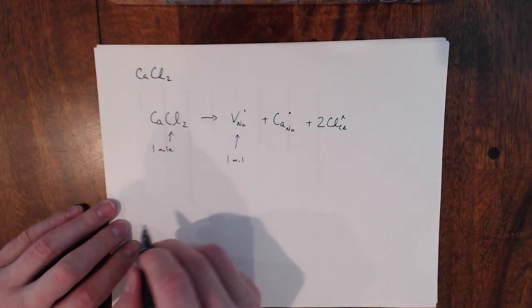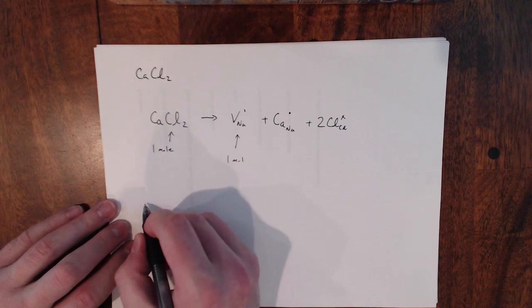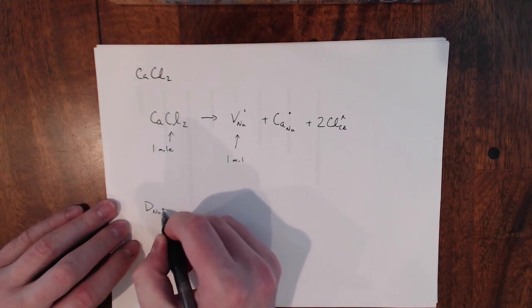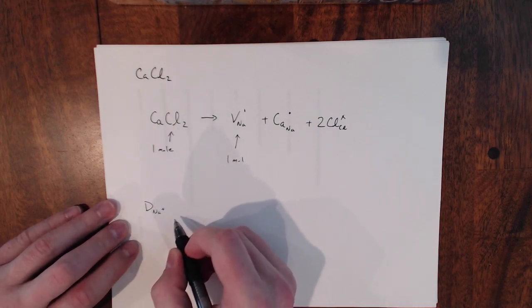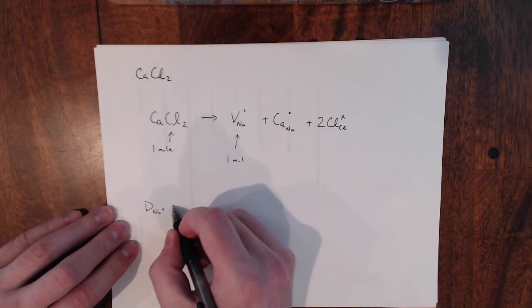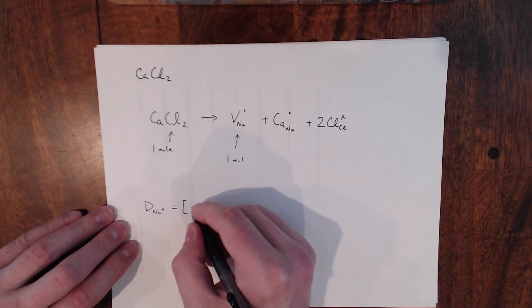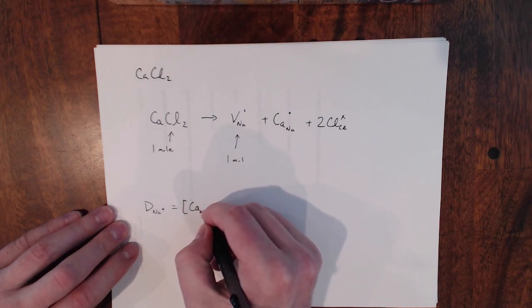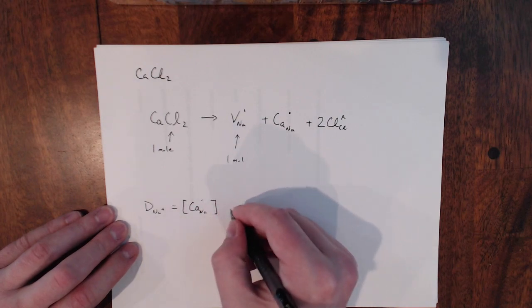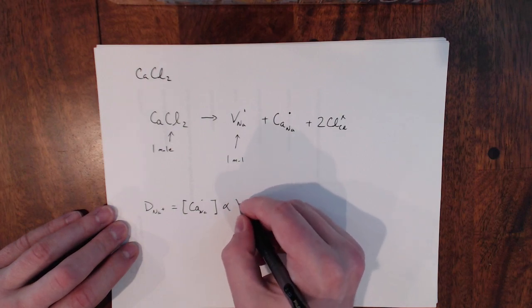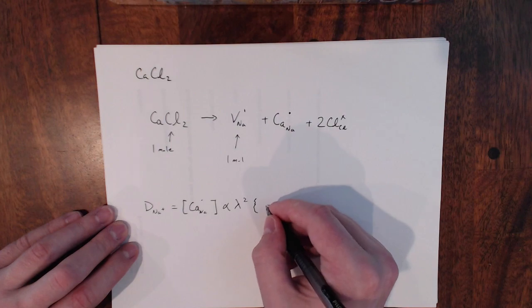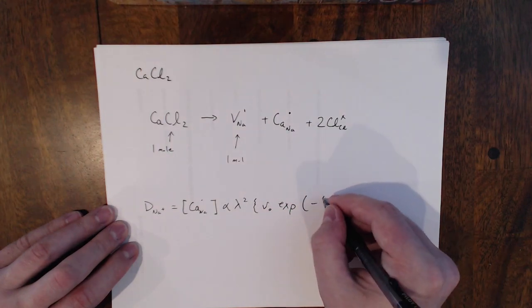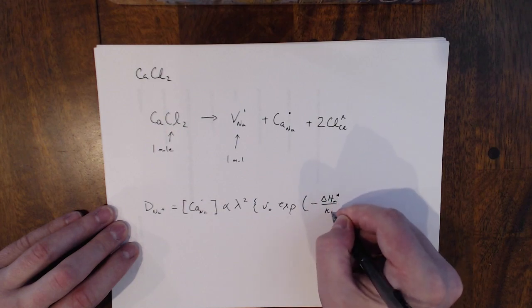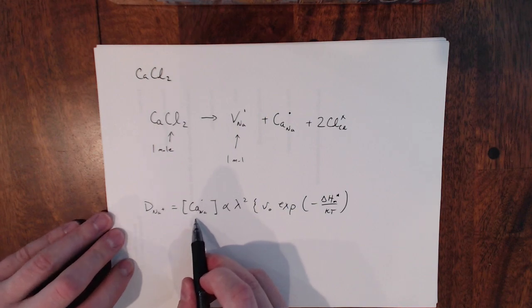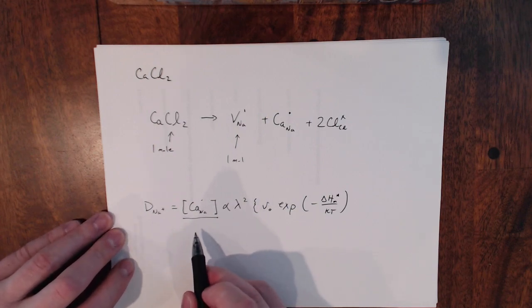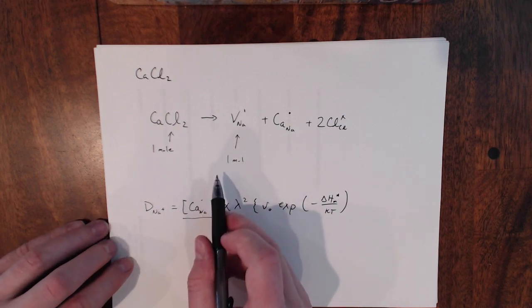And so now that I know my connection of the sodium vacancies, I can now again write a similar expression for the diffusivity of sodium ions if it's governed by this type of site fraction. So now this is going to be equal to the concentration of calcium in sodium. Again, this is that 1 mole, and then multiply by alpha lambda squared, the squiggly term, nu naught, and the enthalpy term, the exponential, right? So the site fraction which we use for capital lambda has now become this part of the expression, right? So it's governed by this reaction that we have up there.